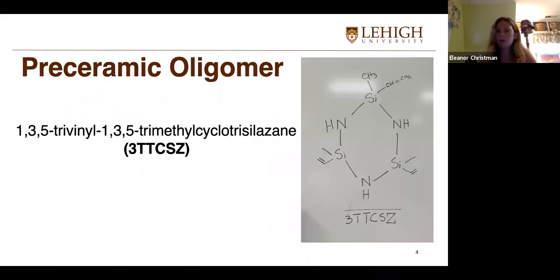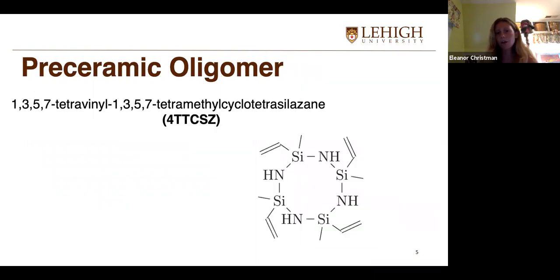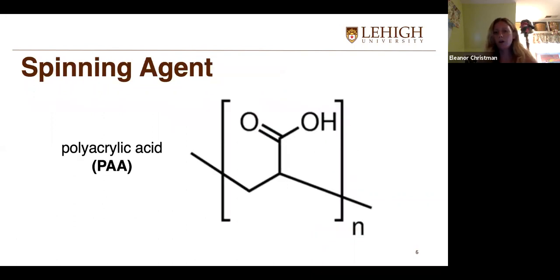So I was assigned this preceramic oligomer, which is 3TTCSZ. It's a 3-membered silazane ring. And I was given this because a previous graduate student, Zankan, was working on this similar preceramic oligomer, which is 4TTCSZ, so it's a 4-membered silazane ring, so quite similar, and we thought that it would be a good comparison point and sort of interesting to see what effect the size of the ring has on all of these spinnability and the cross-linking behavior. So I sort of went off of his recipe and used the same spinning agent as him, which we need to use to be able to spin the fibers. So I used PAA, which has this structure here.